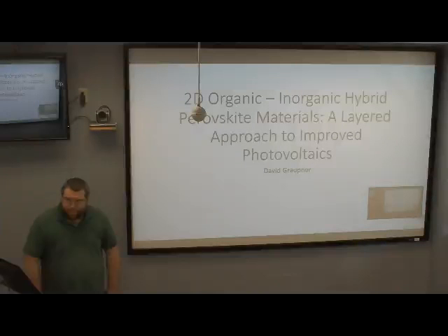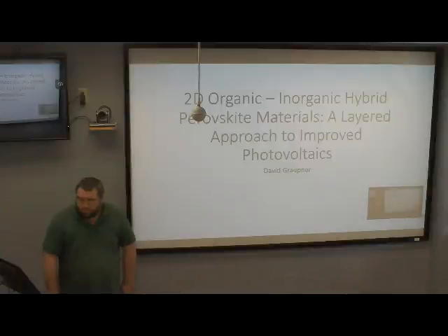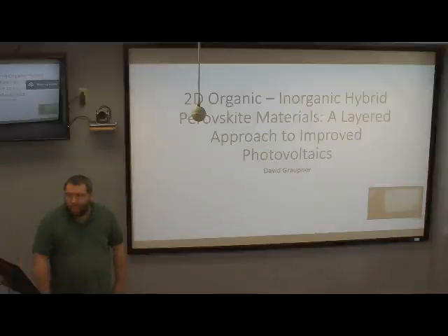Yeah. And if you have a layer structure, even if it is scratched, it will dissolve the first layer and then it stops dissolving, because the hydrophobic ligands will prevent water from going further. So it's much more insulated, and it is one of the benefits. And you can say it, right.